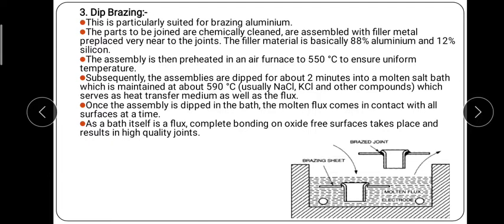So in this, first the metal to be joined is cleaned. Then it is filled with the filler material near the joints. The filler material is basically 88% aluminium and 12% silicon. After assembling, the filler metal and the metal to be joined are passed through the air furnace for preheating, maintained at 550 degrees Celsius. After passing through the air furnace, it is dipped in a molten salt bath which is maintained at 590 degrees Celsius for 2 minutes.